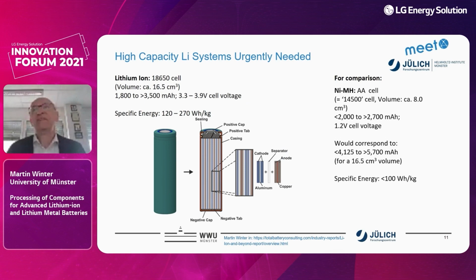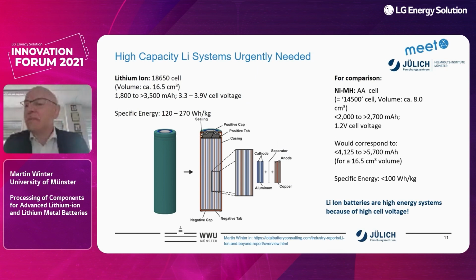So what we can take from this slide is that lithium-ion batteries are high energy systems because of high cell voltage. And it also tells us why we are so urgently looking at higher capacity anode and cathode materials, because capacity is really the bottleneck, not voltage, at the moment in the present lithium system.